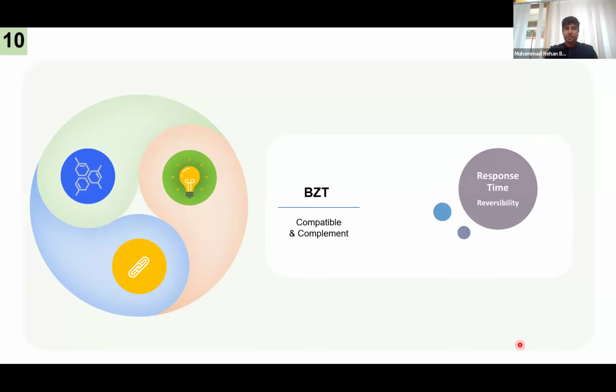And BZT is quite a promising material. Our research group recently showed, before this research, that if we put BZT within the polyethylene, it can actually increase the transparency of the polyethylene in the visible region. That was one of the attractive things for our research work, because we want our polymer films to be transparent so that light can transmit through them. What happens when BZT goes into the polyethylene is that it goes into the microvoids that were created because of the chain orientation, and that reduces scattering, because of the matching refractive index of BZT with polyethylene. Because of this, the light scattering is reduced and the polymer transparency is increased.